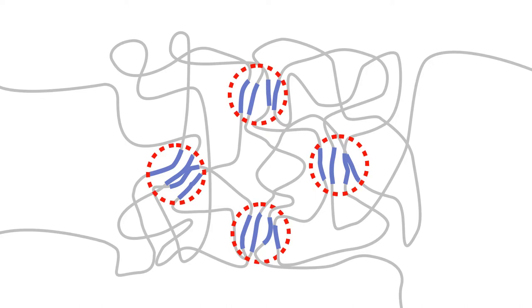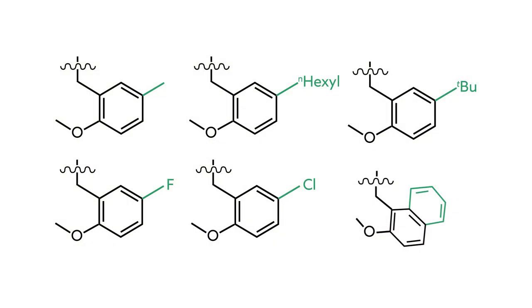X-ray data suggests that the shorter bits tend to cluster into crystalline islands in an ocean of the longer and more flexible component. That clumping tendency is believed to be the force that drives the material to heal itself after being cut or broken. But the polymers proved capable of much more.